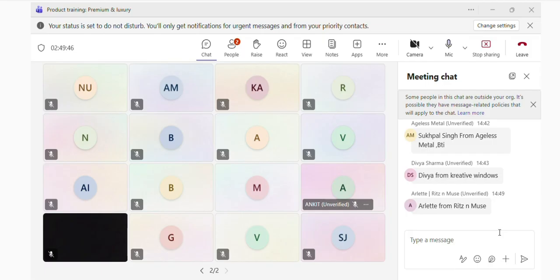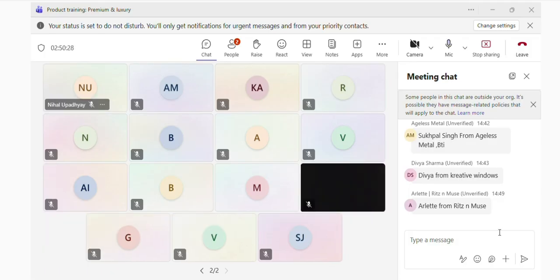First of all, you are not aware of the quality of extrusion, of the alloy used. You say you are using 6063 alloy, but that will be a mixture of scrap material. The quality of extrusion is not that good. If the quality of extrusion is bad, there are two issues. One, the coating issue will be there. The absorption of material on the metal is poor, and that can cause corrosion issues later on. But if the material is virgin, good quality extrusion, your absorption in the metal is better, then you have a better quality of coating, and the life of your window will be more.